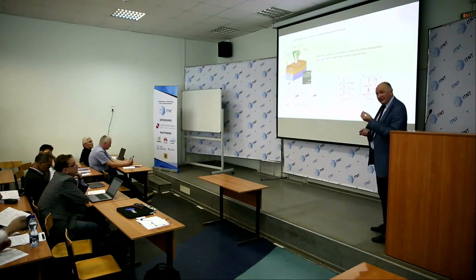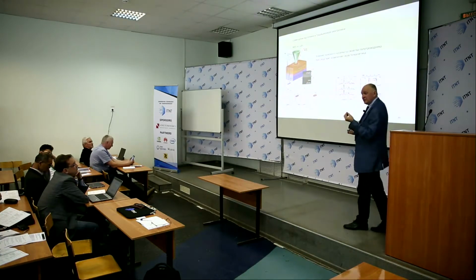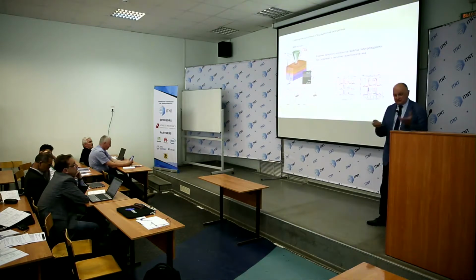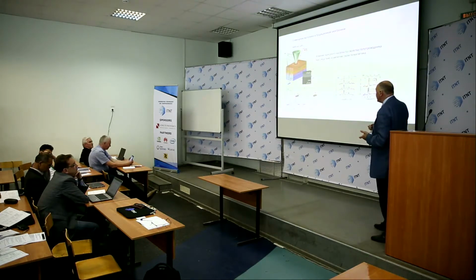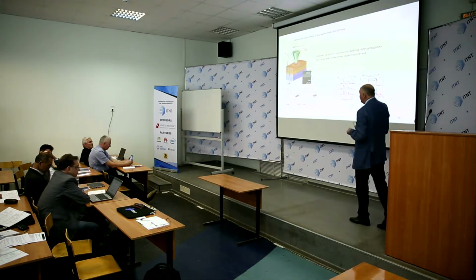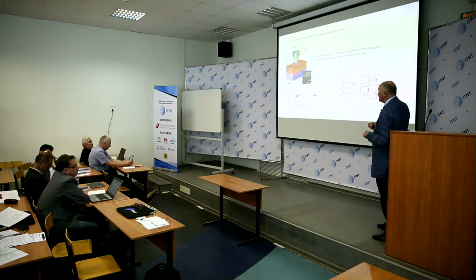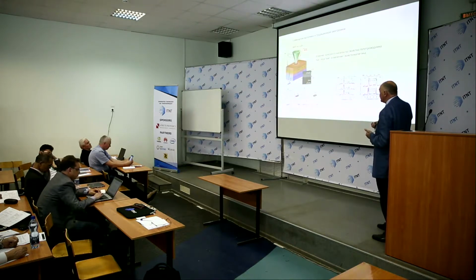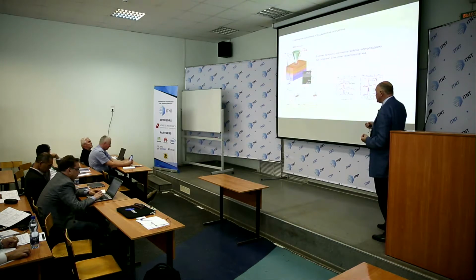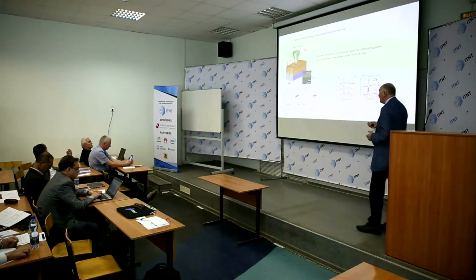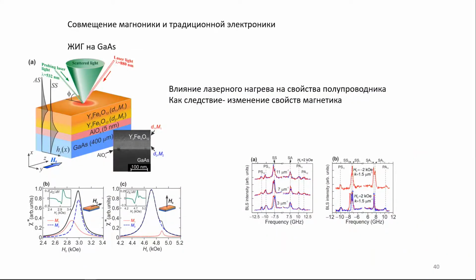But gadolinium gallium garnet does not belong to typical microelectronic materials. The typical materials are gallium arsenide or silicon. Therefore, we started to produce yttrium iron garnet film on substrates of gallium arsenide. This is one of the typical examples of how we produced this film. And by optical light, we can also excite changes in the density of states of electrons in gallium arsenide.